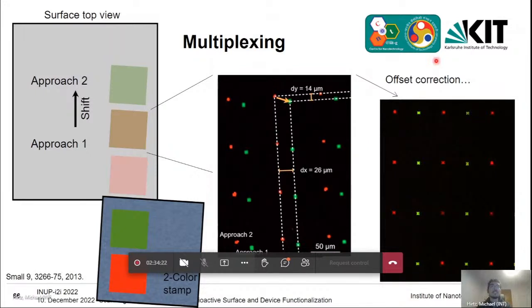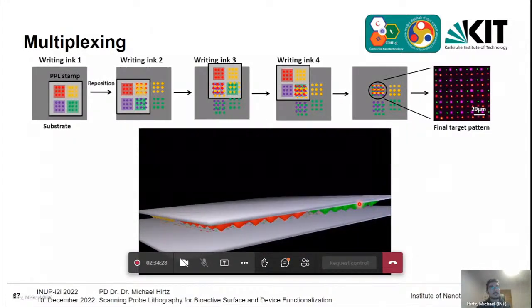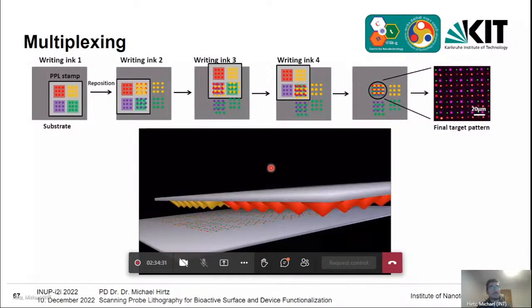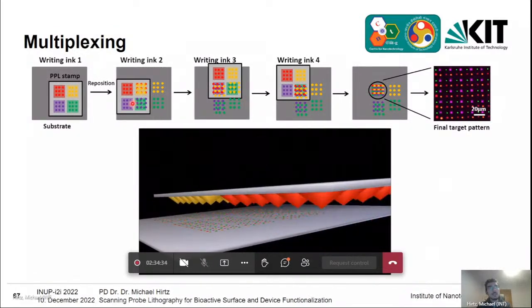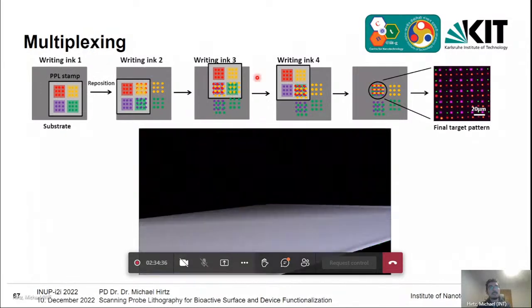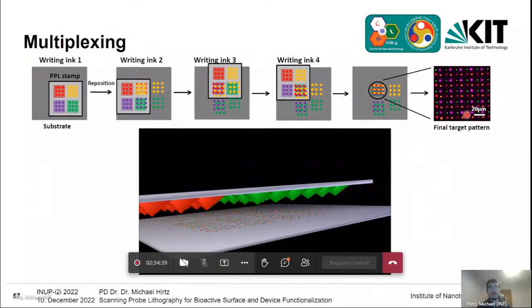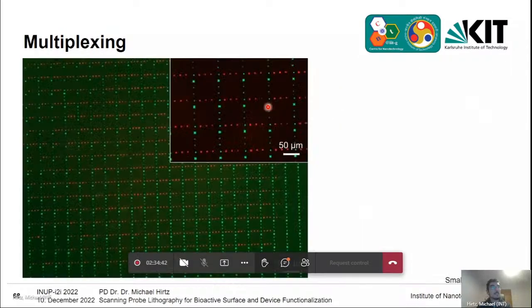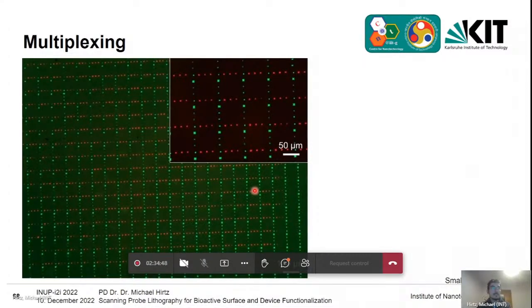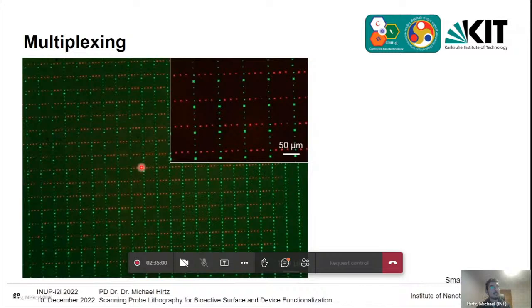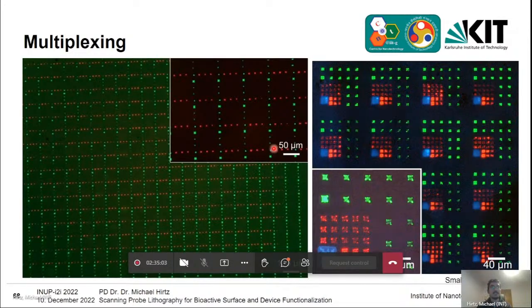There is an offset correction needed, but then you can have nicely aligned patterns. And of course, that's not only with two inks, you can also do it with four inks or even more. It all depends on the size over which you can reliably move your stamp to achieve your target pattern. So we can achieve very large patterning here, also over square centimeters. Here we look at an area where the two patterns merge together, and here you would now have millimeter to centimeter scale patterns of this kind over the rest of the substrate.